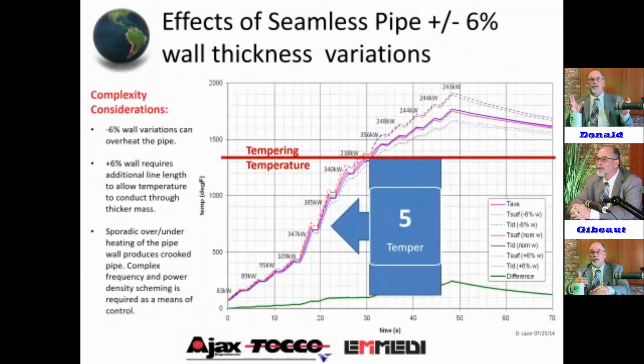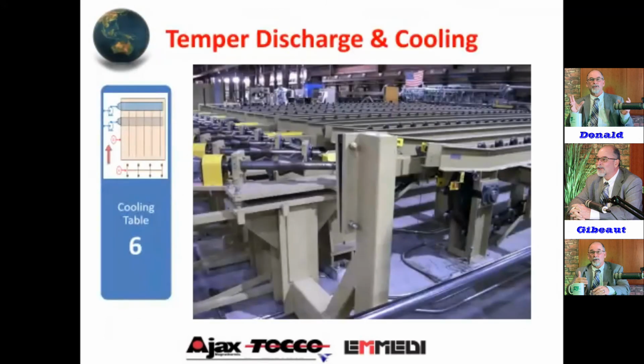I did have some discussions this week at Tube 2020 with a vendor that can, with a magnetic coil, actually look at that wall variation of the seamless. On the in-feed side, before we heat it up, we were talking about maybe putting that there and getting some feedback to help increase the line speed on seamless tubing because of that wall variation. Because if we can verify what the wall variation is, we can manipulate this power density curve to increase the line speed.